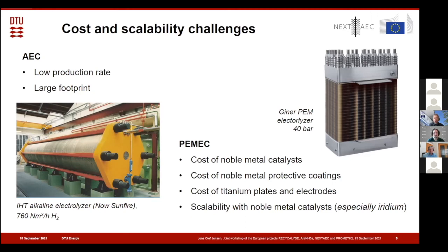The new boy in class among commercial electrolyzers is the PEM electrolyzer, which has gained very high popularity because it's so much more compact and has a lot of advantages. It's really a nice system, but it also has some challenges, which we have heard a little about already, with the noble metals. The catalysts are noble metals, and to my understanding, there are many groups trying to solve that problem or replace the noble metal catalyst, but we haven't seen that happening yet. So we are still stuck with iridium and platinum. There are also noble metal coatings on the internal parts to avoid corrosion, and the plates and the porous transport layer, the electrode structures, are normally made of titanium.